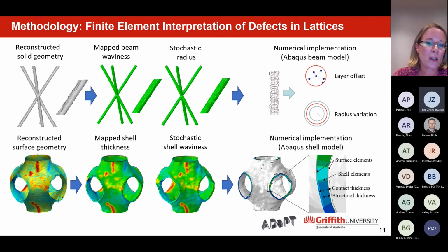Important here is that if we introduce the roughness and thereby reduce the wall thickness, we have to introduce some surface elements to make up for the missing contact surface. That surface element doesn't have mechanical stiffness, but it provides contact stiffness for the densification. So that's important if we reduce the shell thickness.